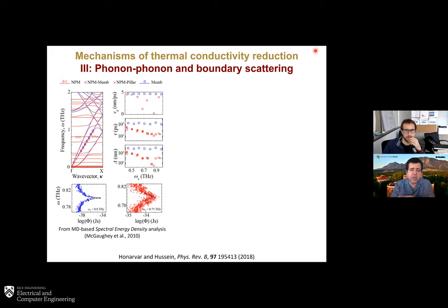So just to show you how this manifests, we have here adopted a technique called the spectral energy density method, whereby, unlike before, we conduct a molecular dynamic simulation, and we use the velocity fields from the simulation and effectively apply a space-time Fourier transform. And in doing so, in the frequency domain, we can get the properties of these phonons. And unlike the previous work with the transport model, where we have to make assumptions on the scattering constants or maybe curve fit them from experiments, here it's all happening dynamically based on our choice of interatomic potential.